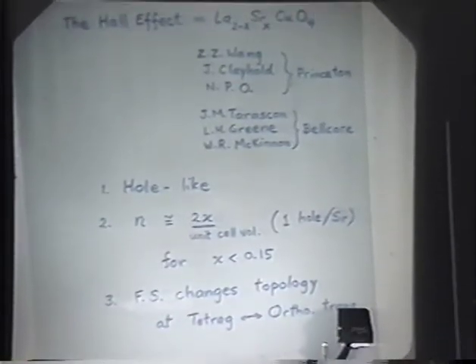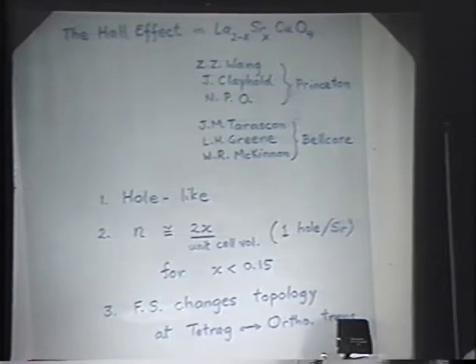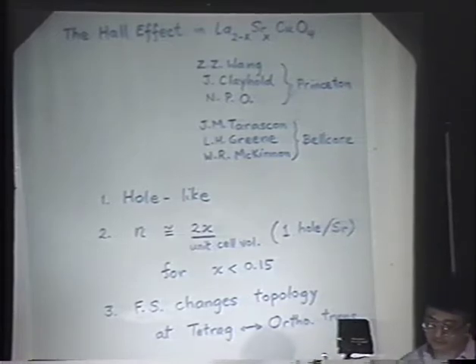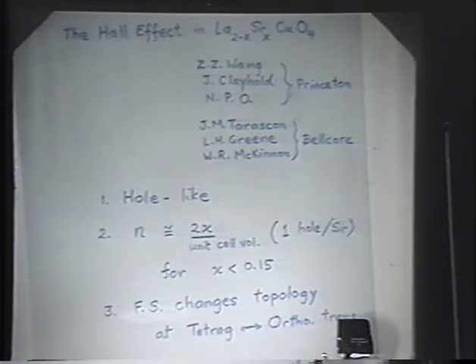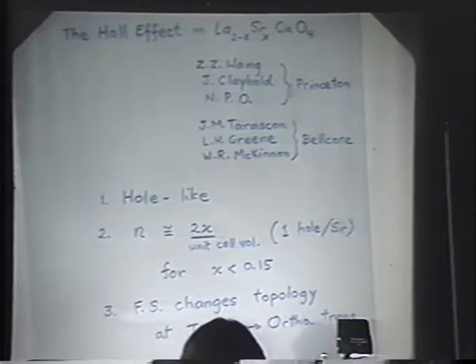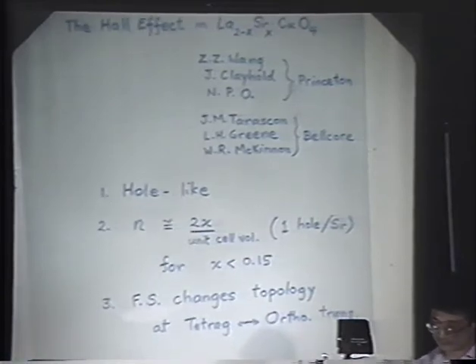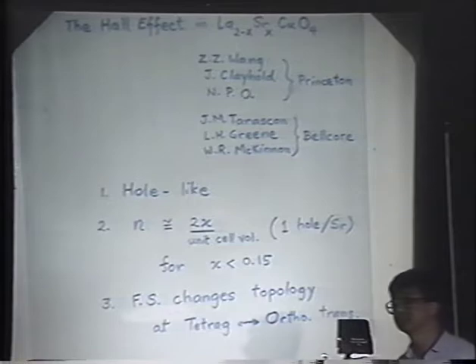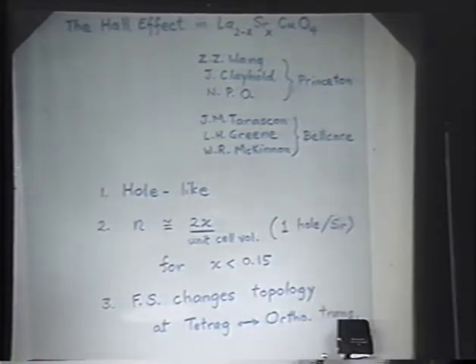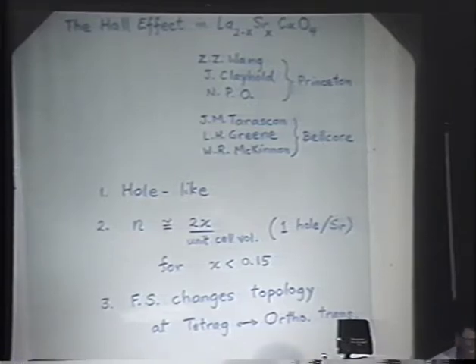and the density actually increases as you dope it very close to the line that you would expect from the rule that you get 1 carrier per strontium atom, until you hit the composition 0.15, where we think we're starting to see the orthorhombic to tetragonal transition, and then something mysterious happens. The Hall signal vanishes. We believe that it drops below our level of resolution, and we think that this is an indication that the Fermi surface is undergoing a topological change, and the Hall and thermal power are sensitive to this change, whereas resistivity will not be. And I'll discuss a little bit the implications for Fermi surface induced instabilities in this system.